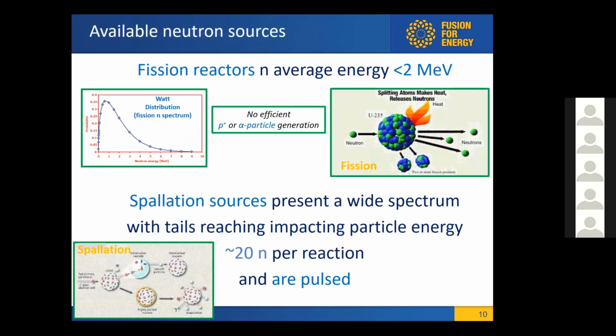And as you know, the fission reactors have a neutron average of below 2 MeV. So this transmutation of iron into chromium doesn't take place, basically. And spallation sources generate above 20 neutrons per reaction and are pulsed, which is also a problem because we have seen some hysteresis in the materials, by kind of self-annealing when they are not irradiated. So the degradation of the materials is very much correlated with the steady state of future fission reactors, and not with a pulsed nature.